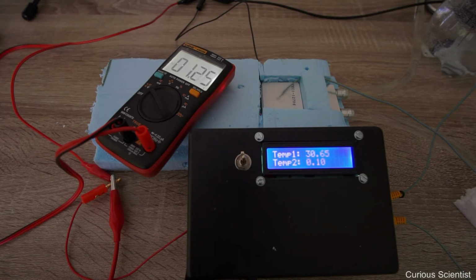And you see that there was like 2 volts in the beginning, and now it's decreasing and decreasing. Now 0.7 volts, 0.6, and the temperature on the cold side is rising. Now we have like 0.25 volts. 0.1 almost, and you will see that the voltage will be 0 if the two sides are at the same temperature, because there won't be any temperature gradient, therefore there won't be any voltage produced.